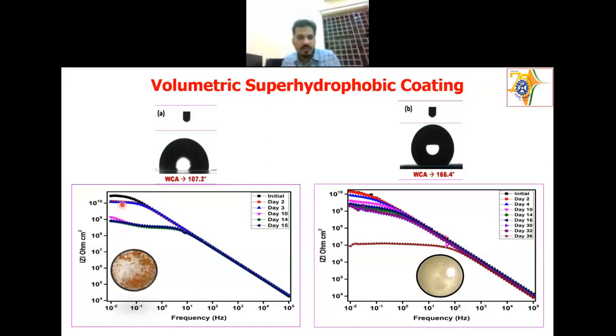Here we found that corrosion products appear on the exposed area after day 14 in the case of the hydrophobic coating. In the case of the super hydrophobic coating, up to day 32, it has very high corrosion protection. On the 36th day, we found that it got reduced, but there were no corrosion products. So we can say that PDMS-based coatings will have a lot of pores. Through the pores, oxygen can go inside and undergo oxidation, and corrosion may start there. That is why we got the decrease. But still we couldn't find any corrosion products here. This work is in progress right now.